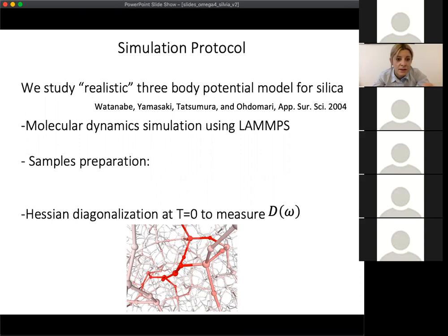This is very important because ultimately we want to understand the general features of glassy materials. We would like to develop an understanding of glass in a generic and comprehensive way. This is our first step. Here is our simulation method: we studied a realistic three-body potential model for silica proposed by Watanabe, Yamasaki, Tatsumura, and Ohdomari in Applied Surface Science 2004.